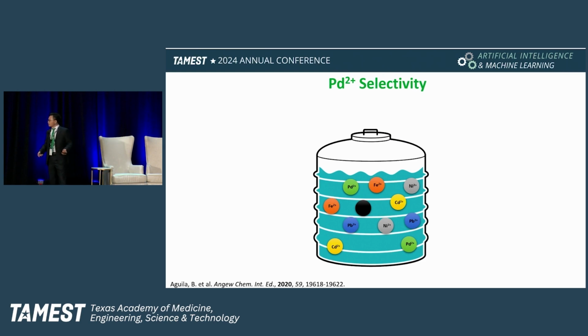Okay, in addition to this, of course, we always know in the e-waste there's a mixture of different metals, particularly some other metals: iron, nickel, cadmium, etc. We found that for our other material, this is not really good, but for this polymer with amino and pyridine groups, it can still do a very good job. In the presence of so many competing ions, they can still recover the palladium from 5 ppm to less than around 1 ppb. That means the recovery efficiency is still more than 99.9%.